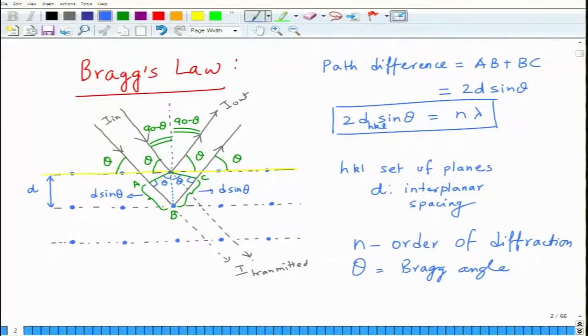d_hkl is not a random value, okay? So if you have 100 plane, if you have 110 plane, if you have 111 plane, and so on and so forth, they have specific values, right? Specific values will mean you have specific d_hkls. Specific d_hkls will mean you have specific theta values to satisfy this equation, because lambda is fixed, okay? So for a given value of n and lambda, your d sin theta product has to be equal to n lambda divided by 2.